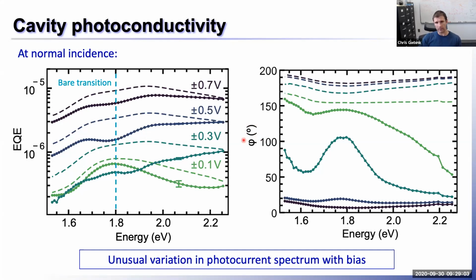The phase of the photocurrent, so this is the phase relative to the chopper that we're using at 400 hertz, also undergoes dramatic variation spectrally. So the phase of the photocurrent when you excite at, for example, red light is different than when you excite with green light. This is also very unusual because all the dynamics that are happening with these Polarons are picosecond, nanosecond timescale, and yet we're seeing effects on a millisecond phase timescale for our 400 hertz chopping.